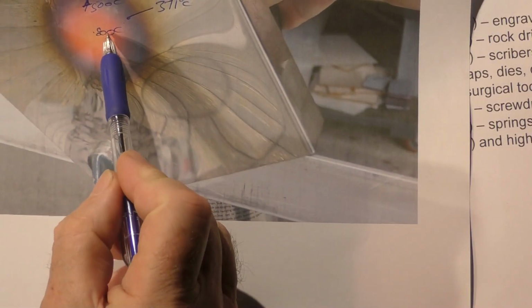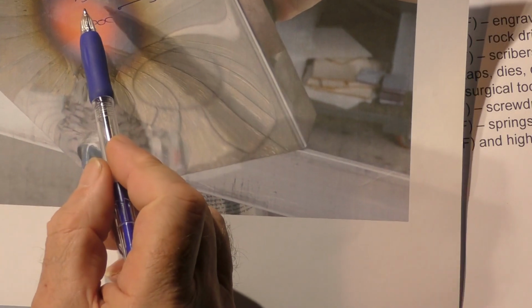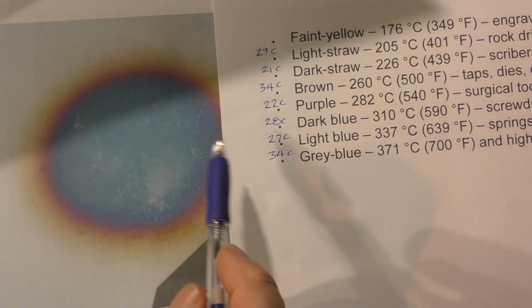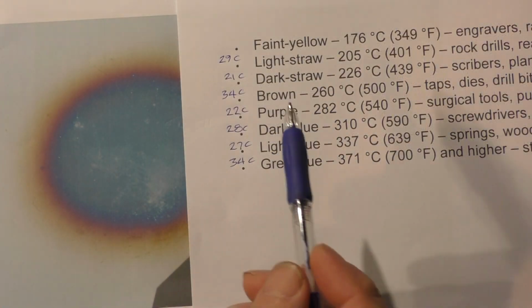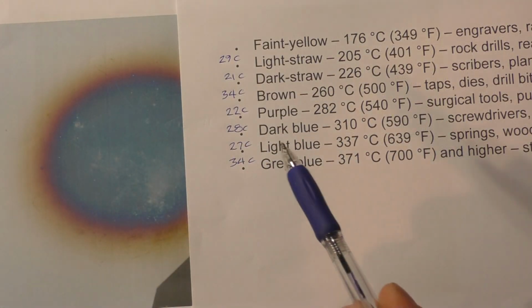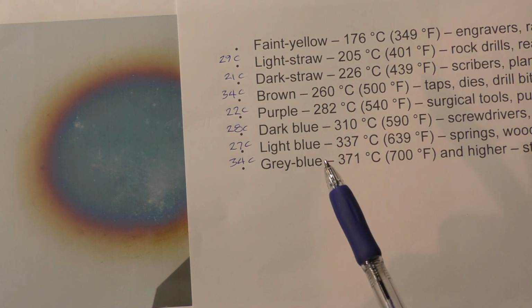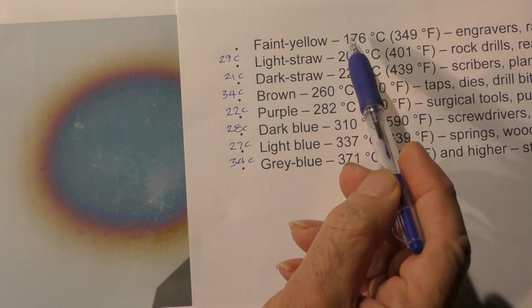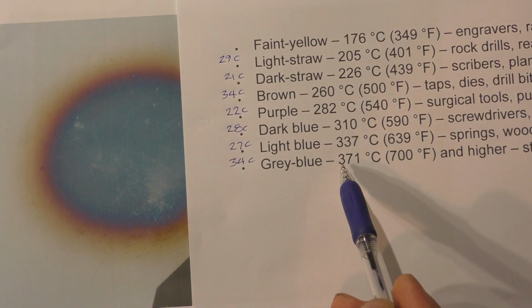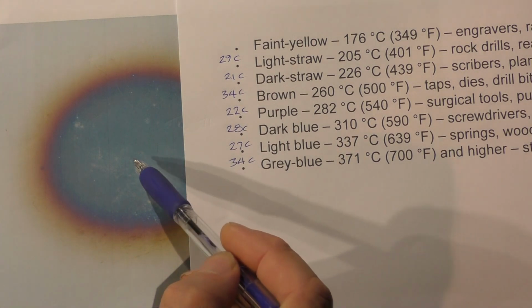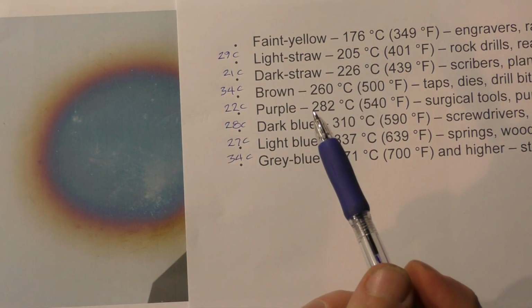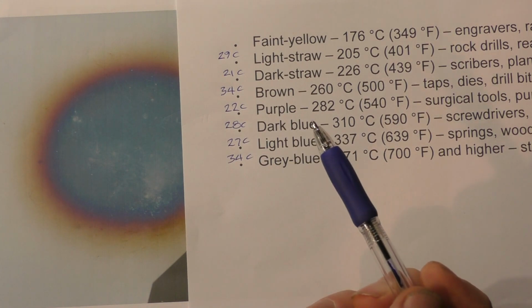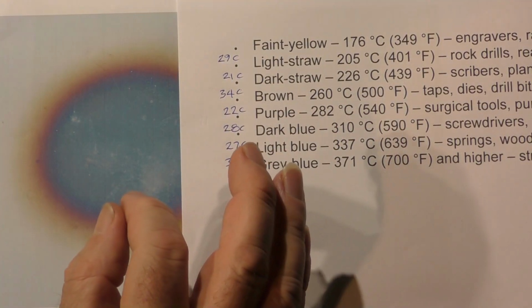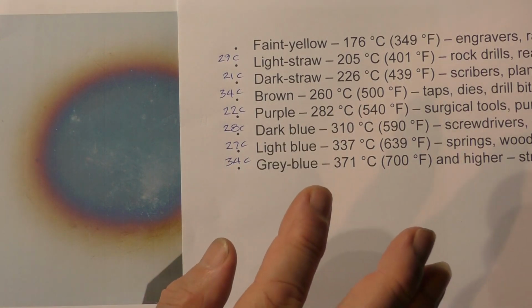371 degrees. It's rather interesting because look, we've heated that all the way up to 800 degrees C and 500 degrees C in the middle there. As it cools down to 371 degrees C, it creates this colour. So the thing I want to emphasise here is we've created these colours with a blow lamp, a very crude instrument. But it does require these temperatures here, up to 371 degrees C, to produce these colours. Now, as I explained to you in the previous session, temperature is only a function of the vibrational level of the material. So 371 is not very hot.